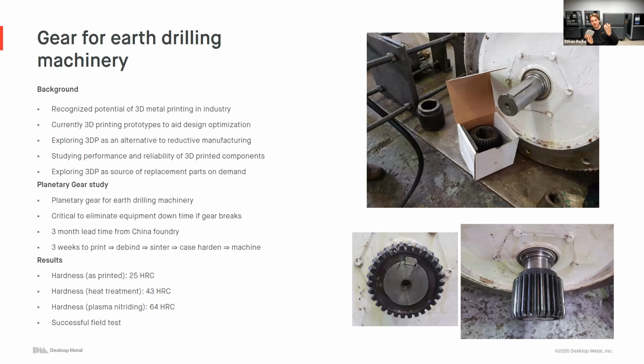So what did that 3 weeks entail? It entailed printing this part. It did have to go through a debinding step because it was using an earlier version of the studio system. They then sintered this part in the furnace. They did a case hardening operation to bring up the hardness value on those teeth to ensure it had a long lifetime. And then they did some post machining to ensure that it was hitting all the critical dimensions that they needed. It's quite a big part.